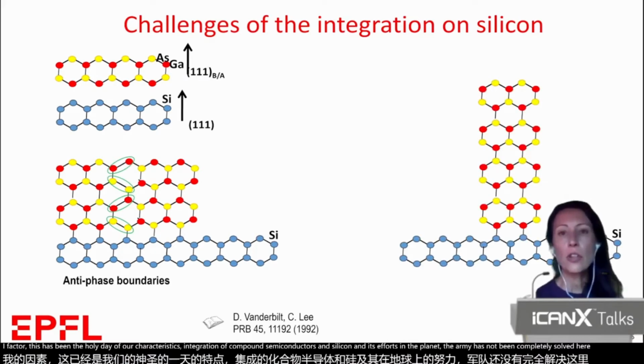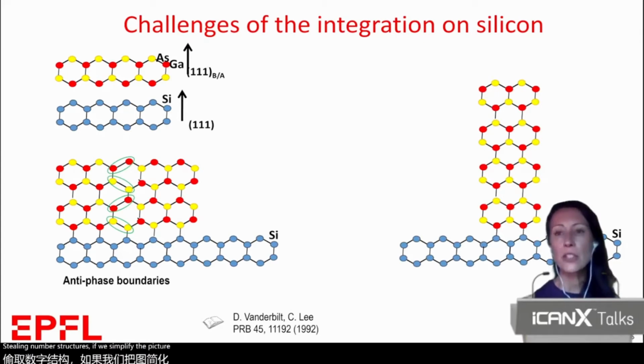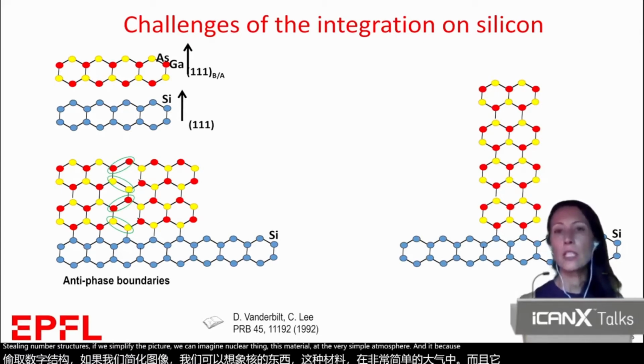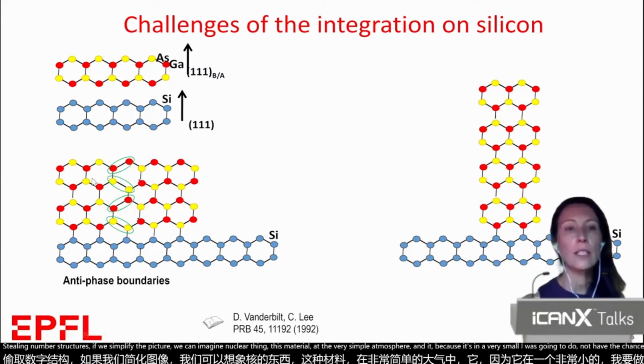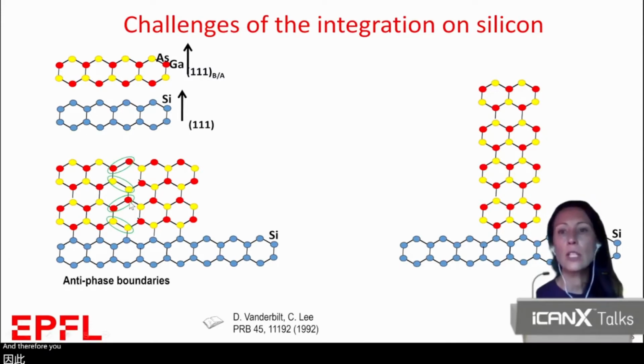Still, in nanostructures, if we simplify the picture, we can imagine nucleating this material at a very small nanoscale. Because it's at a very small nanoscale, you don't have the chance to create these defects, and therefore you get rid of these antiphase boundaries that really kill the functionality of the compounds.